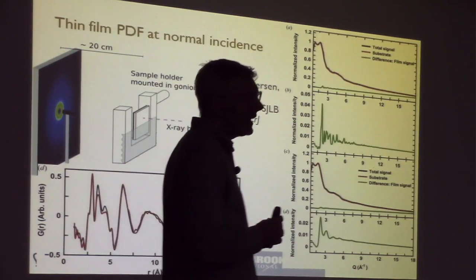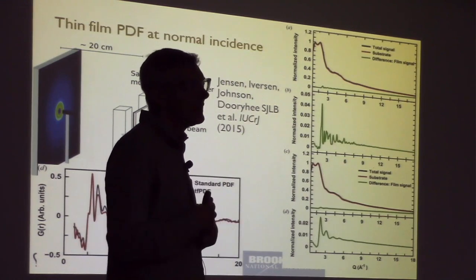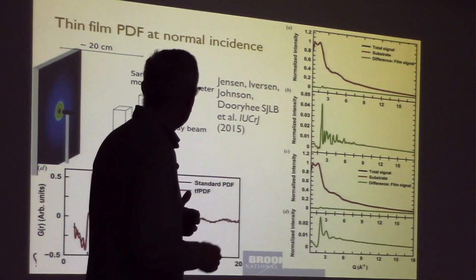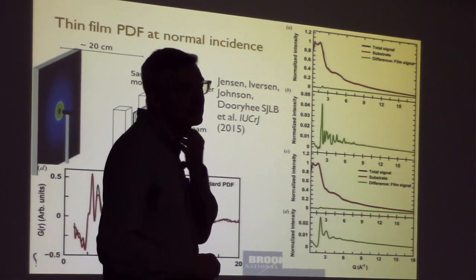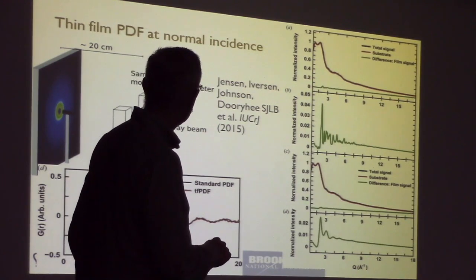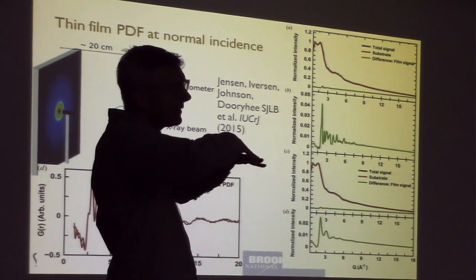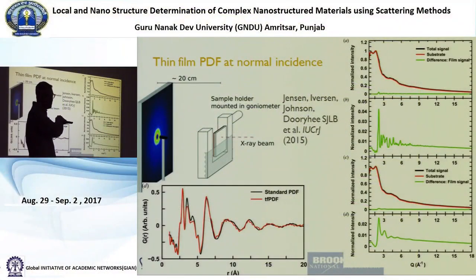So once we had the idea that we had very good sensitivity, and we could see very weak signals in some materials, we said, let's try and do thin film PDF. What we can do here is take a substrate and lay down a film on top. The film will be some nanomaterial, but it's very, very thin. And we come in with the X-ray beam and go through the substrate and through the film and collect the diffraction pattern. Now the signal from the substrate is much stronger than the signal from the film, but because we have this sensitivity, we can do it. And this is an example here where the red curve is the substrate and the black curve is the film, and they lie basically on top of each other.